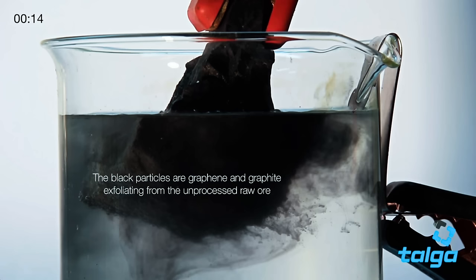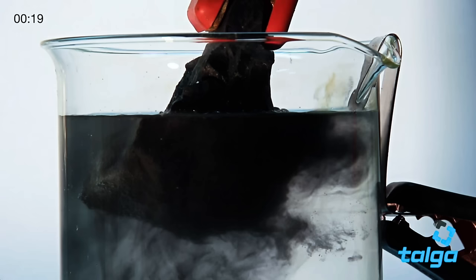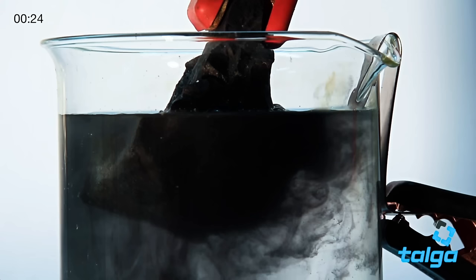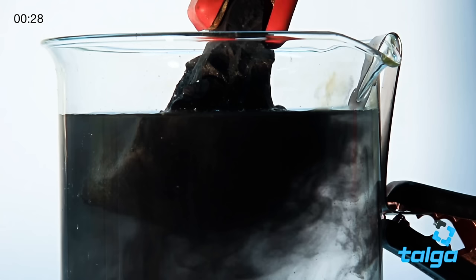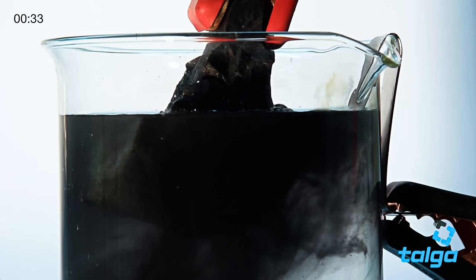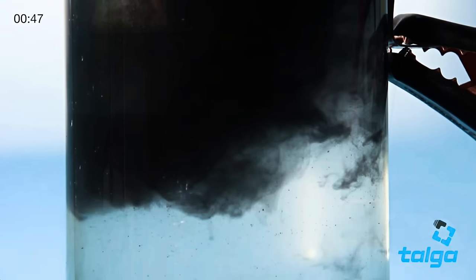This is possible because the graphite ore that Talga has access to is conductive straight out of the ground. When the ions from the solution are driven between the graphene sheets and the graphite, they react in the solution to form gas bubbles. The gas bubbles split the graphite layer by layer, causing the graphene to exfoliate. Notice that this kind of looks like ink or powder. I'll explain what this is when we get to ISO standards.